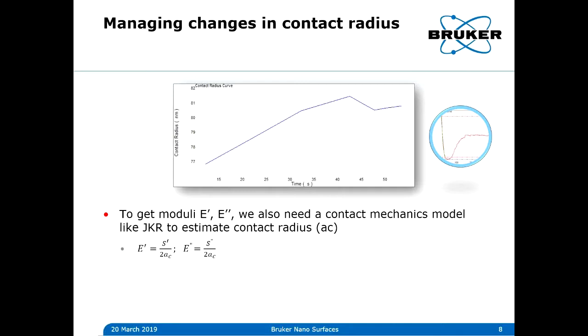The issue is that the samples that exhibit a significant viscoelastic response also exhibit relaxation under load. And this relaxation leads to changes in the contact radius during the measurement. So really we want to be able to know what the contact radius is at every frequency in order to get the storage modulus at every frequency. But thankfully, our friends at Hysitron also work with indentation of viscoelastic materials, and they've helped us to develop some strategies to solve these issues with creep at long time scales.